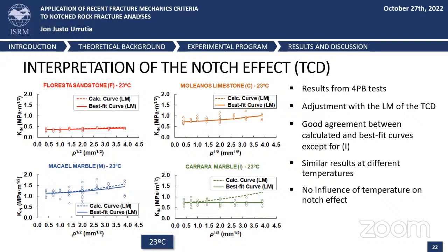And we understand that somehow that ratio for us is, for example, related to the critical distance or to the area that we average for the strain energy density method, the area that we average the energy. And that is in turn related with the grain size. So the ratio between the direct tensile strength and the fracture toughness is more or less constant, but it somehow depends on the grain size.